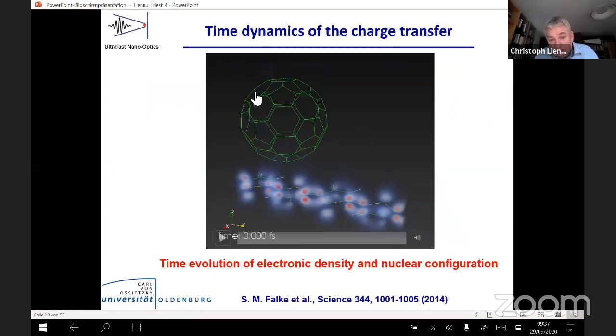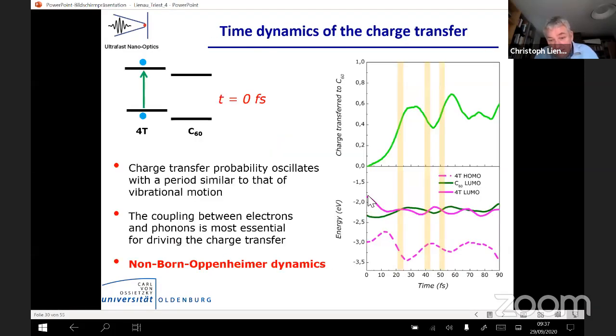We have tried to optimize this geometry, and of course, any variation in position that would necessarily occur in the real system would slightly change the energetics. So there will be disorder in this energy difference, but the important thing is that the system does not care about this disorder, because as you can see, the strength of the electron-phonon coupling is of the order of a few hundred millielectron volts. So even if this initial level splitting here is changing by, say, 100 millielectron volts, the overall dynamics would not.